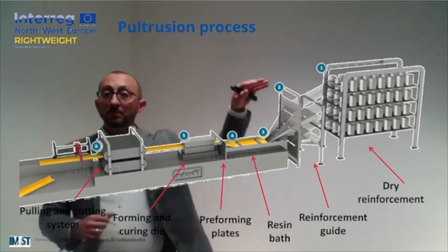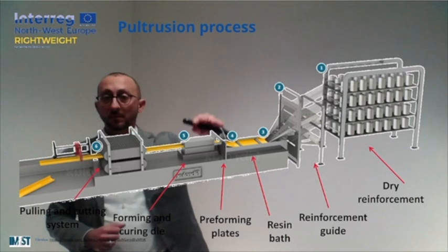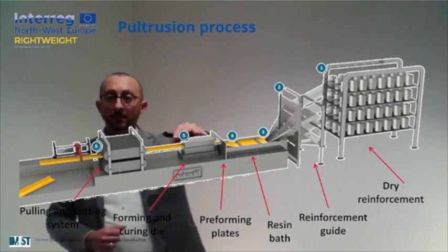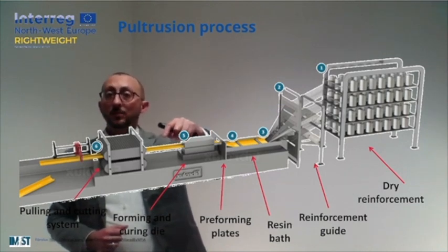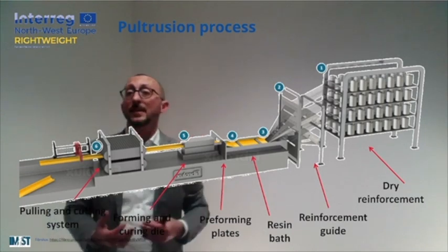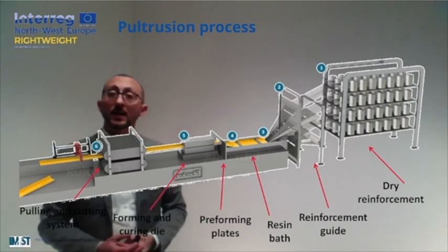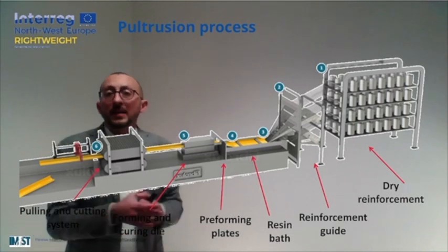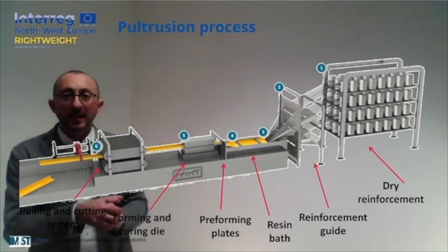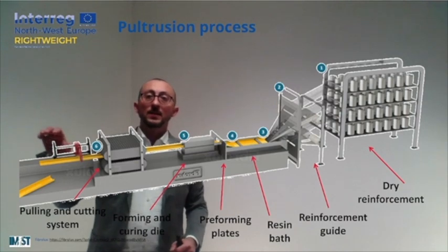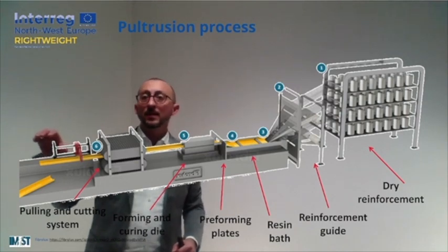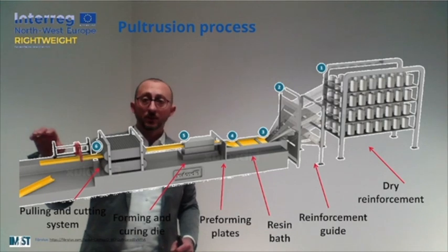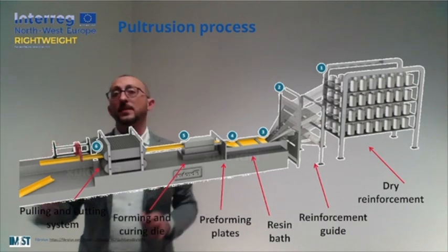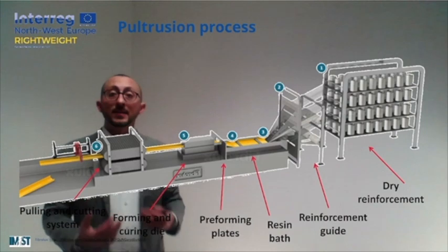And on the other edge of the line we have the dry reinforcement, and since in pultrusion the typical shape of the reinforcement is in the form of continuous fibers, you can imagine that this traction load is propagated along this line, and the dry reinforcement is continuously pulled through the different stations in order to achieve exactly the 3 steps I was mentioning before. So impregnation, shaping and solidification. At the exit of this element here, that is our heating and curing die, the complete pultruded material is a completely vitrified solid, and it can be easily clamped and pulled. At the end of the line, it is typically placed a traveling cut-off saw that is used, of course, to cut our profile at the desired length.